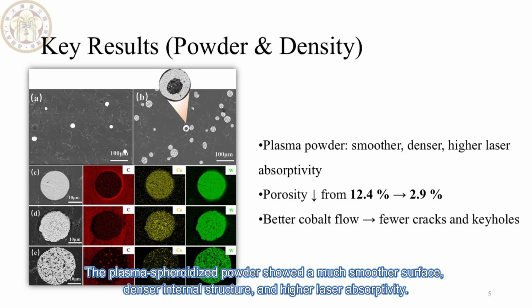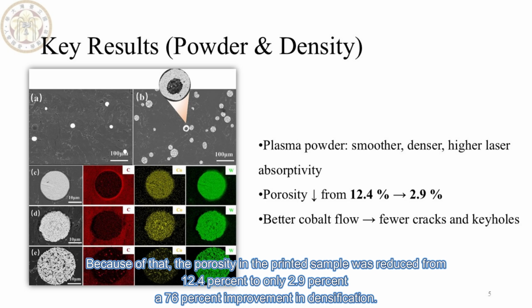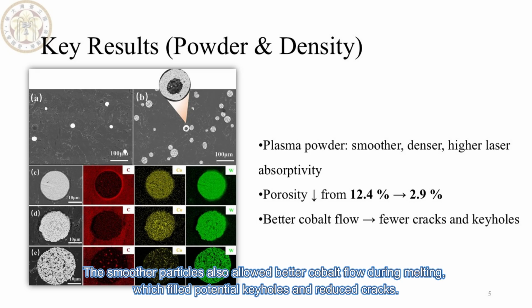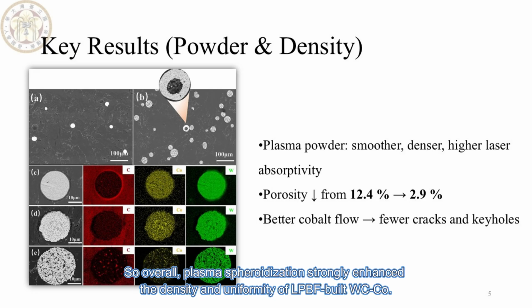The plasma spheroidized powder showed a much smoother surface, denser internal structure, and higher laser absorptivity. Because of that, the porosity in the printed sample was reduced from 12.4% to only 2.9%. A 76% improvement in densification. The smoother particles also allowed better cobalt flow during melting, which filled potential keyholes and reduced cracks. So overall, plasma spheroidization strongly enhanced the density and uniformity of LPBF-built WC-Co.